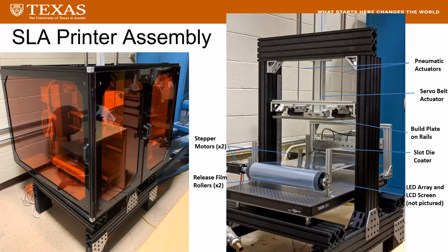So on the right, you can see the whole printer assembly, where the light patterning components that I just discussed would be illuminating in an upwards direction from below the release film. That's not pictured in this image, but it is there. This type of printing, since we are intending to cure paste-like resins, we can't use a resin bath like is typical in SLA systems, because the stiffness of the uncured resin often exceeds the stiffness of a cured elastomeric structure.